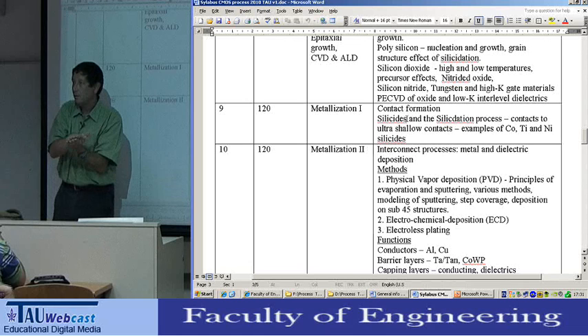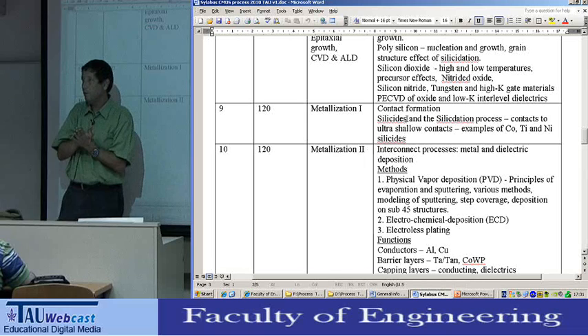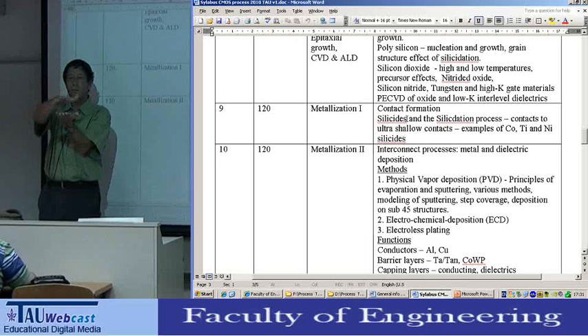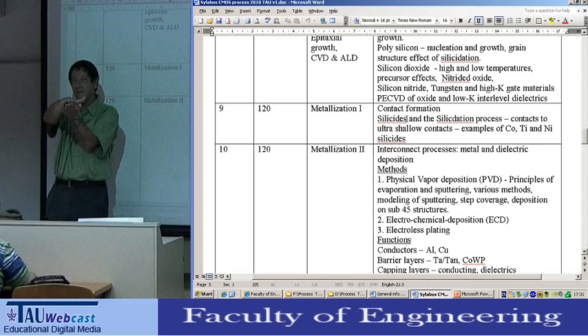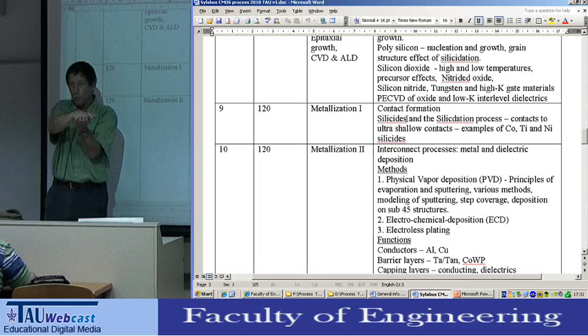Now, those alloys were a breakthrough about 20 years ago because they make what we call an intimate contact. If you put a metal on the silicon, sometimes you are not sure the metal is touching. But if the two metals react chemically and you make an alloy between the two components, then you are sure that the metal is touching the silicide, which is touching the silicon. So you have an intermediate layer.